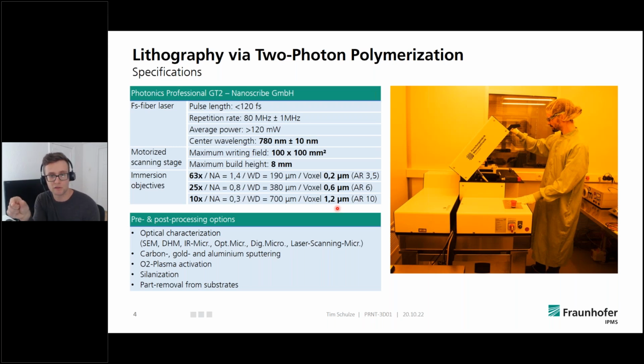So it's 1.2 micrometers wide and approximately 12 micrometers long. So in case you want to print something with a really, really high resolution, you should really consider the orientation of the printed object. Here, and on the other hand, we tried to